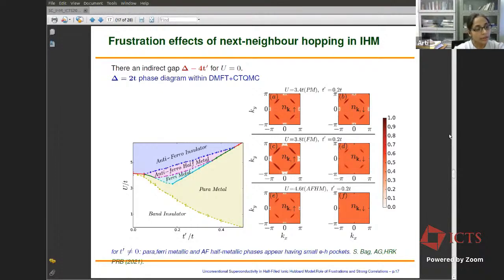So although with the help of second neighbor hopping at finite electron-electron interaction, one can induce these ferrimetallic and antiferromagnetic half metal phases, all these metallic phases are kind of compensated metals with very small Fermi pockets. They don't have a large connected Fermi surface. So this is something to keep in mind, that we are always getting a compensated metal even at the intermediate strength of the electron-electron interaction.